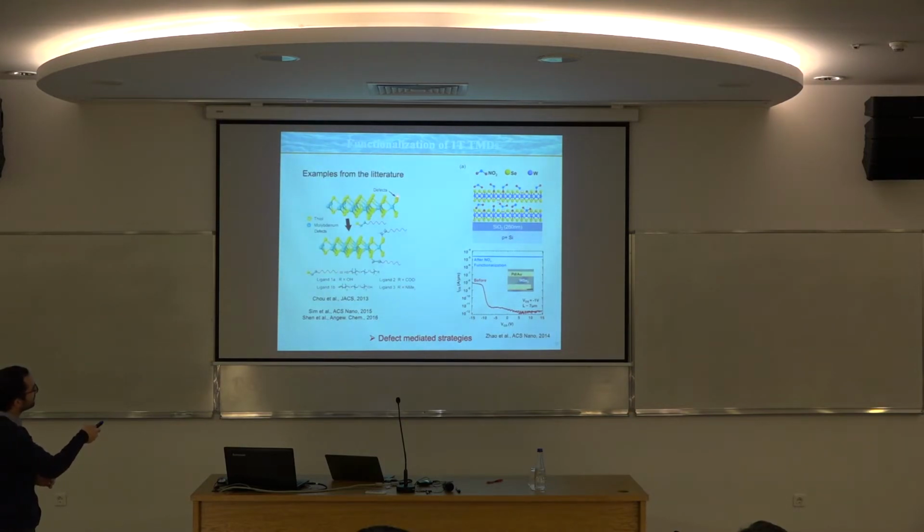So when you have sulfur vacancies, people have predicted that this thiol can react and then coordinate at the vacancy site, and it could be a way to actually heal the nanosheets. So after you have this functionalized TMDs where this thiol is coordinated at the defects, you do a mild thermal treatment, and this group leaves, and then you have healed the sample.